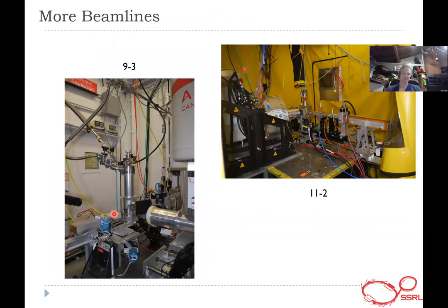So at 9.3, you can see there's a liquid helium cryostat, 100 element detector. 11.2, this is a giant yellow tent you can see surrounding it. And before the slits, which you saw in 4.1, is a harmonic rejection mirror. And so we bounce the beam off of this to get rid of harmonics. It's a rhodium-coated Zerodur mirror, and we can change the angle of that before it hits your sample, getting rid of harmonics, and a different format of 100-element detector that we also have.